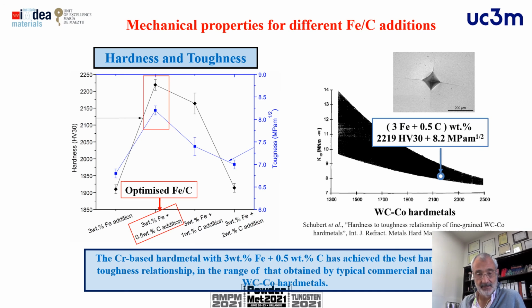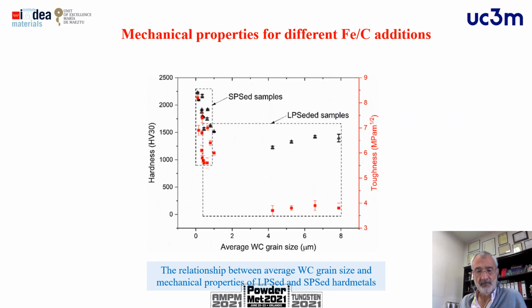So these values, this is the optimized material, can be plotted here in this graph, in which we can correlate the fracture toughness with the hardness, and we are just in this point that we can compare our result with some conventional tungsten carbide with cobalt, conventional hard metals. Here we can compare the difference that we reach with the spark plasma sintering samples with the liquid phase sintering samples. The average grain size is much higher in the liquid phase sintering than the spark plasma sintering, and that allows us to have much higher hardness with a good combination of fracture toughness.